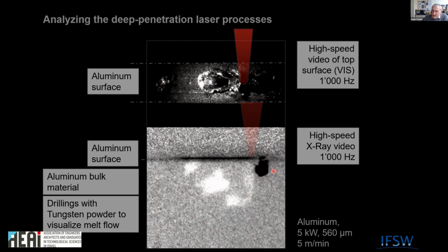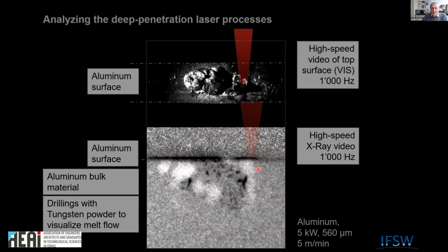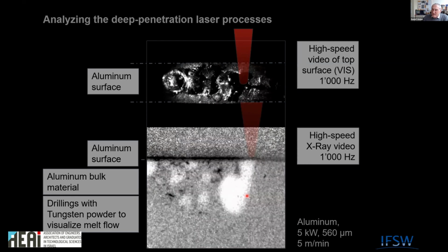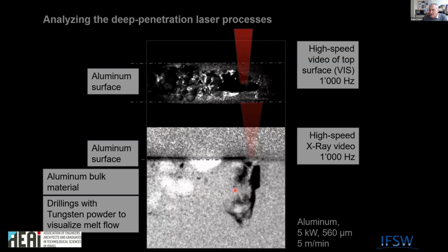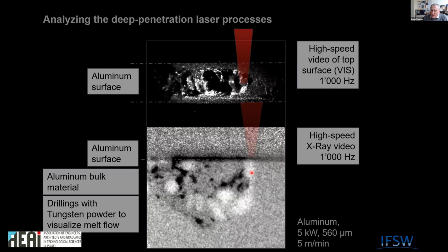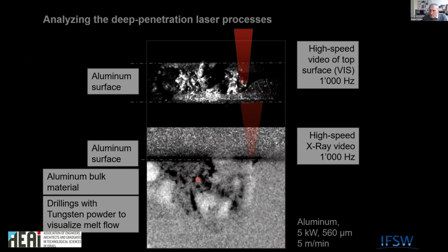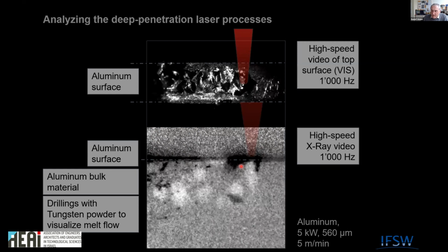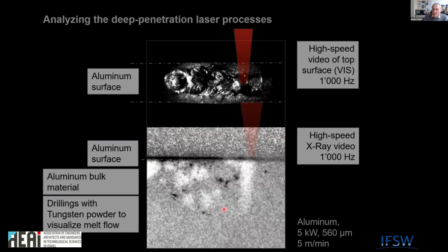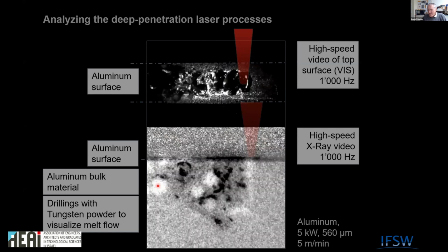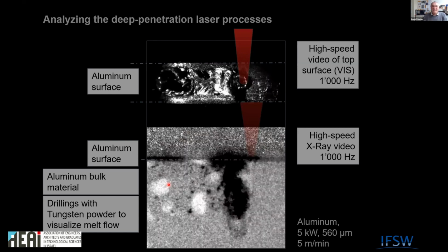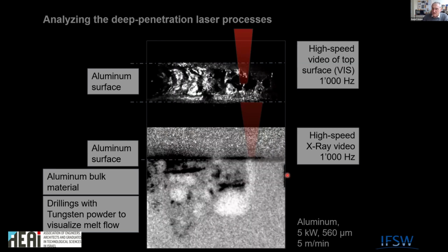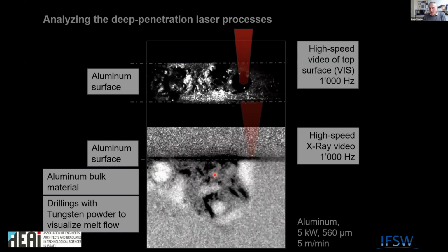Therefore, we have here a drilling. This is a mechanical drilling, which is filled with tungsten powder, which does not melt. And what you can visualize now is what's going on inside the melt. So you see, whenever we go with the beam through this tungsten powder, you can really nicely see how chaotic, let's say, the whole fluid flow in this hot molten aluminum is, how you create eddies, and also how you create so much of pores. So this is an idea. You will see today a lot of such images and pictures that you get an understanding where we come from.